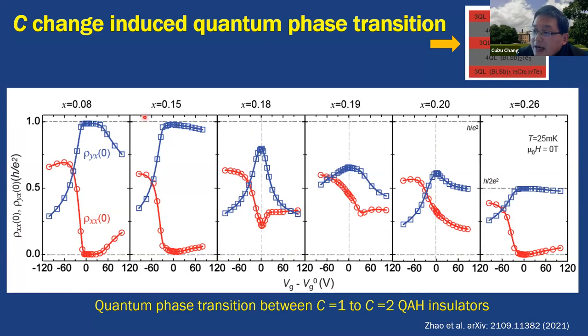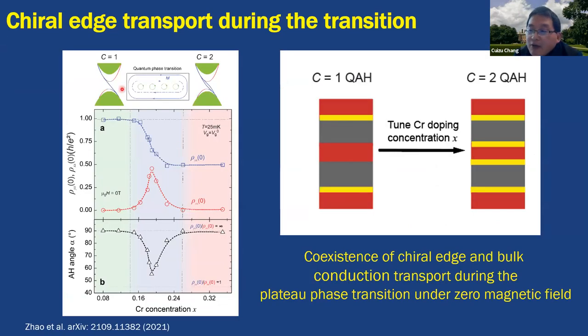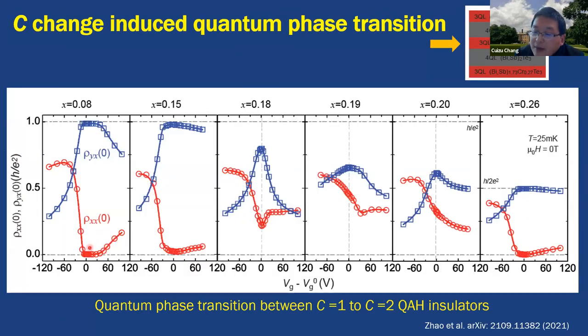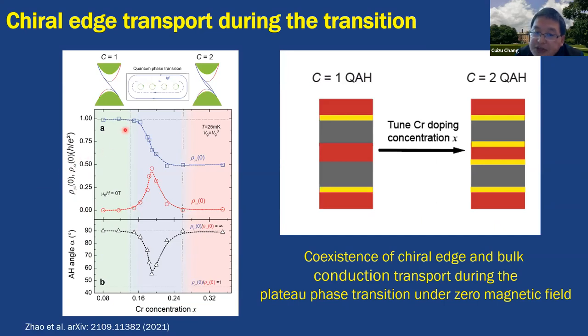And for the 0.26 doping level, it shows the C equals 2 quantum anomalous Hall state. And from 0.15 to 0.2 doping level in the middle, we indeed realize the quantum phase transition from the C equals 1 quantum anomalous Hall insulator to the C equals 2 quantum anomalous Hall insulator. So let's summarize the zero field Hall resistance and longitudinal resistance as a function of the doping level. We can see that when the doping level is below 0.14, it shows the C equals 1 quantum anomalous Hall effect. When the doping level is above 0.26, it shows the C equals 2 quantum anomalous Hall effect. When x is between 0.14 and 0.26, it shows the plateau phase transition.